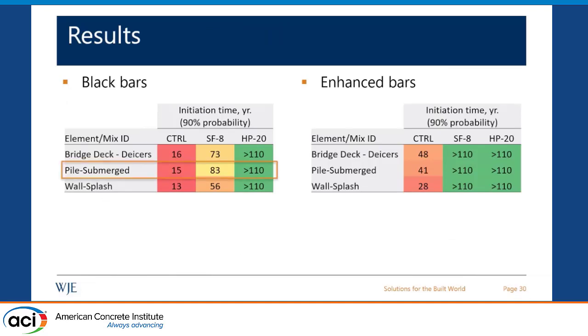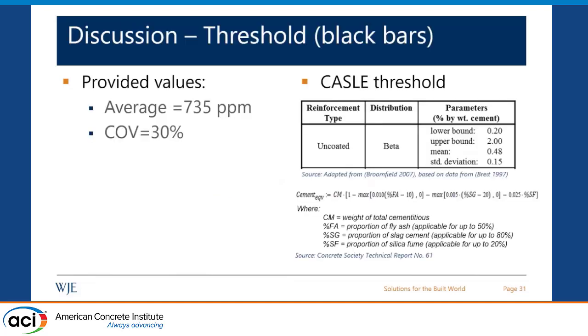And again, looking in more depth at another input parameter. So now let's look at the pile submerged case, and look specifically at the assumed chloride threshold in the analysis. So the provided values that were given for the session had an average of 735 ppm with a coefficient of variance of 30%. So we're assuming normal distribution.